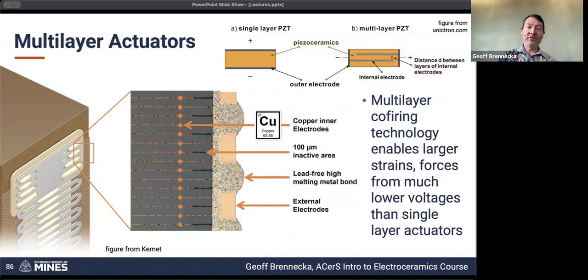Even more impressive, and I want to use this as a transition to some of the actuator and piezoelectric applications that we're going to get to, people have now begun co-firing a lot of these multilayer structures with copper. Copper is very similar to nickel in terms of its challenges, but requires an even lower sintering temperature. So now we have to do all the stuff that we're doing with nickel. We can have just a little bit higher oxygen partial pressure, but now we've got to knock off 200 degrees C from the sintering temperature because otherwise copper will melt. And so the fact that people have been able to make these multi-layer actuators for piezoelectrics with copper electrodes using the same kinds of technology and tricks that have been developed for the MLCC industry, I think is tremendously exciting.